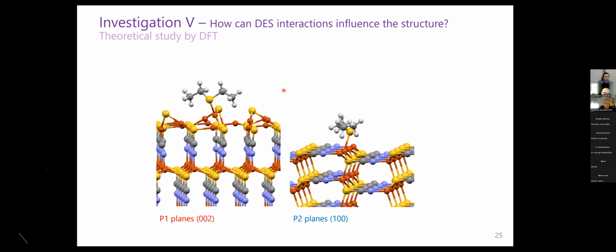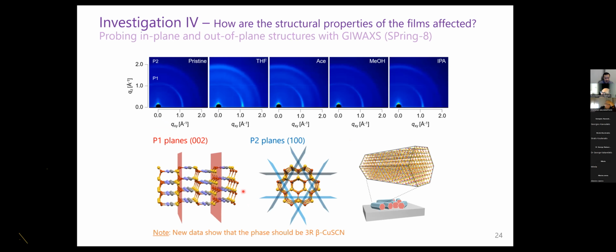And with the collaboration, we then also looked at the theoretical studies. And indeed, the diethylsulfide can coordinate very strongly on the surfaces of CuSCN, especially when the copper atoms are on the top. These two planes actually have higher energy than the other planes that we investigated for the CuSCN. But they can interact with the diethylsulfide, meaning that the diethylsulfide can lower the energy of these surfaces. So they come and bond with the copper and stabilize these high energy surfaces. And these are the same planes that we found from the X-ray diffraction experiments, basically.